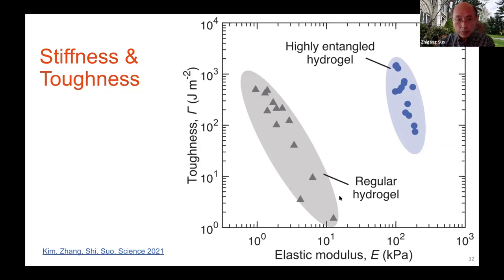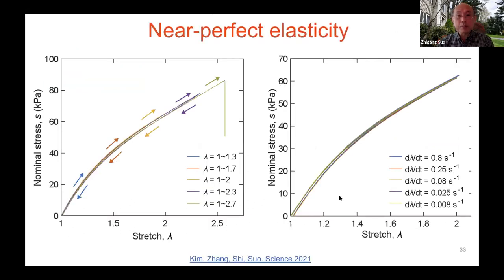Okay, this material is highly elastic, achieving such a high toughness with about 1% of hysteresis. You can see loading and unloading, the hysteresis energy is about 1% of the entire energy underneath. It's a very, very low hysteresis.